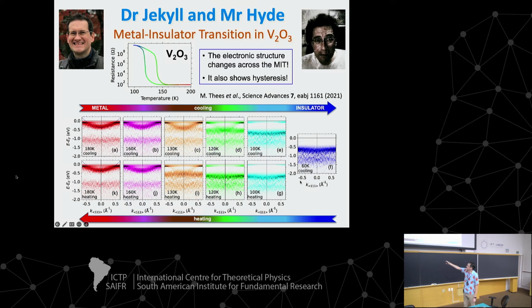So in the metallic state, we have this parabolic-like dispersion, electron-like around gamma, and the Mott-Hubbard band. And as we cool down, you see this parabolic-like state is losing spectral weight, but it's not changing its effective mass or Fermi momentum. It is just losing spectral weight. And a second thing is happening. A quasi-localized state is appearing, it's increasing its spectral weight, and is simultaneously shifting down in energy.